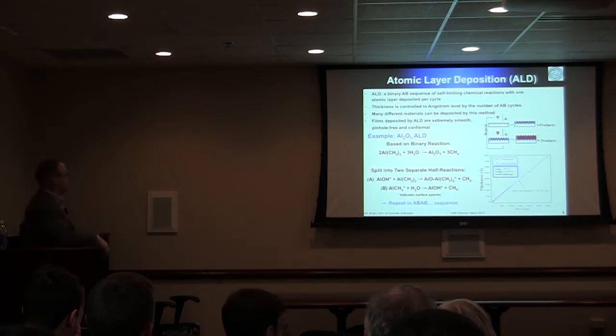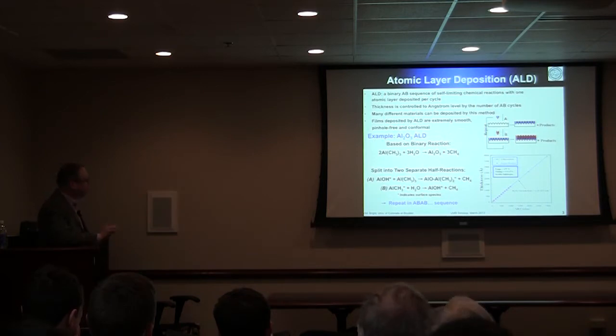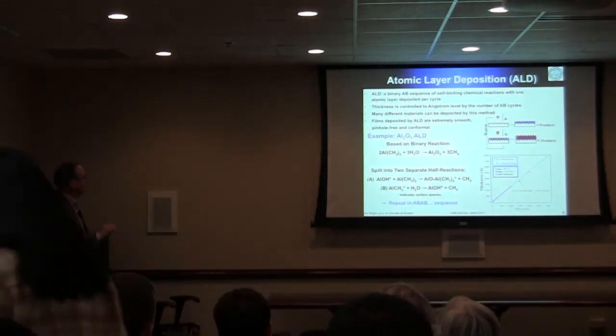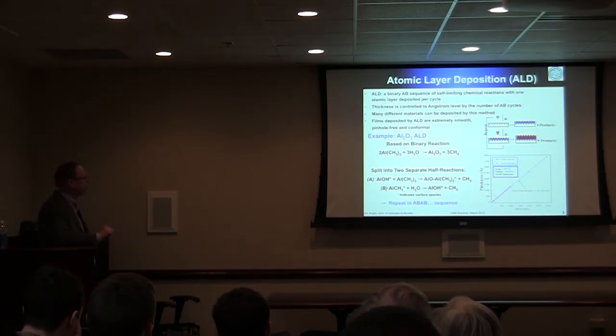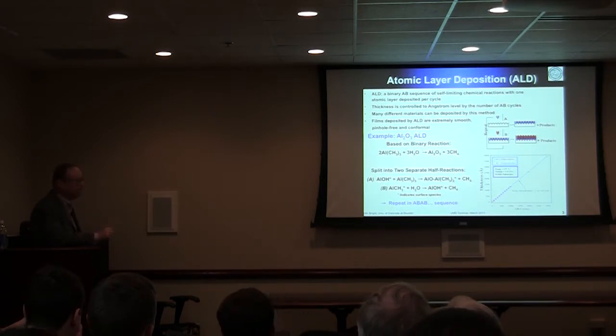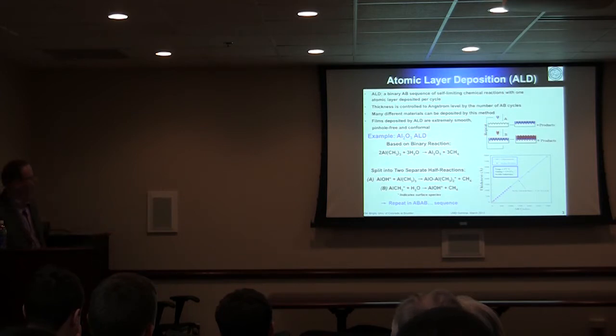So just a brief slide on ALD. People here know what this is, but just a quick review. One nice thing about ALD is it allows a binary sequential reaction. And so in principle, at least in theory, one could build one atomic layer at a time. So you have perfect atomic control of thickness in the vertical direction. The example illustrated here is ALD alumina, which works quite well: theoretically you can get a very precise linear curve of thickness versus the number of reaction cycles.